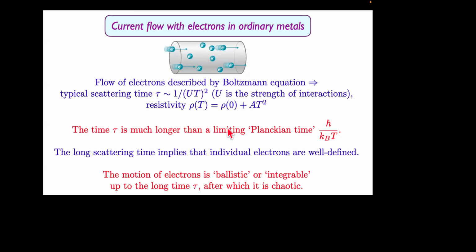Okay. So if you go through this consistency argument, you find that everything is okay as long as this time is longer than what now people call the Planckian time. This is the time that you would make out of nothing but Planck's constant and temperature. So as long as this time is bigger than this, you're okay. And now you see the reason for our confidence in this theory. No matter how large U is, all you have to do is make temperature small enough. Eventually, this time, since it diverges as 1 over temperature squared, will become longer than this time, which only diverges as 1 over temperature. So eventually, at a low enough temperature, Sommerfeld's theory should be resurrected.